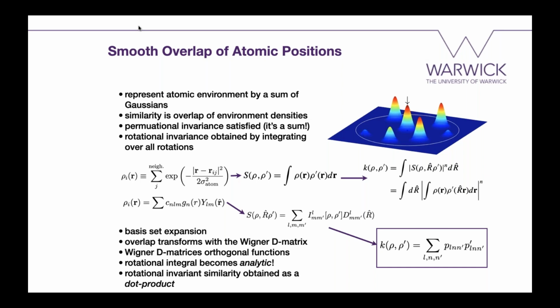So from this, the similarity between two neighborhoods becomes just a simple integral of these densities, which is almost good because it obeys the translational and permutational invariances. Unfortunately, if you rotate one of the environments, it will change. So we have to make it rotationally invariant, which we do by considering all possible rotations and integrating over them. And working through the algebra, it turns out that this can be constructed as a dot product of two vectors which depend on the local environment. So I won't bore you with the details.